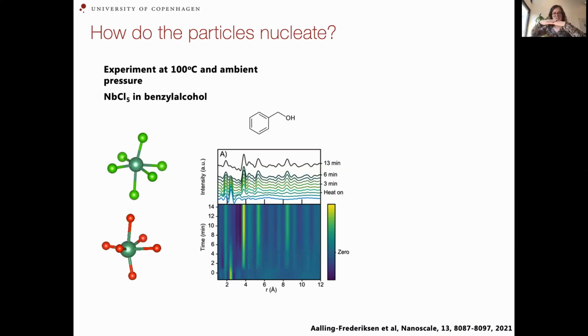So we can look at the crystalline structures, and we can look at how defects develop in the crystalline and nanocrystalline structures. But of course, what we're also interested in are the very, very early stages of the material formation. Here we show the PDFs obtained from an experiment at 100 degrees, so at a lower temperature than before, where we can follow this in a slightly slower fashion. Again, here I have times, so 0 minutes, and here we have the PDF. Our precursor for this is niobium chloride that we dissolve in benzyl alcohol. If you look at these PDFs, there's a fairly sharp peak here at about 2.3 angstrom.